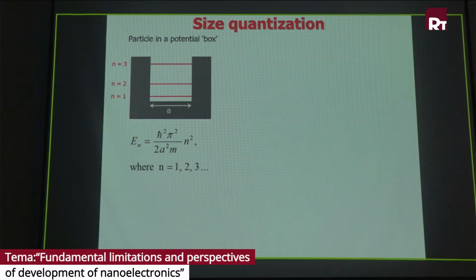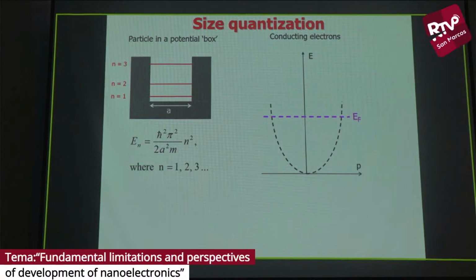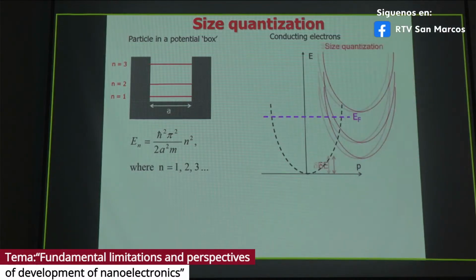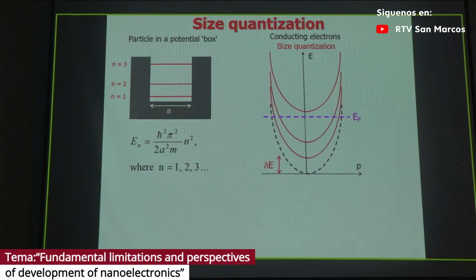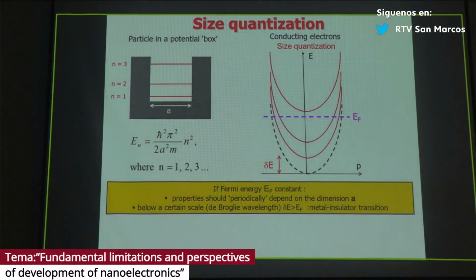Let's recover conventional textbook quantum mechanics. If one takes a quantum particle and puts it in a quantum well of dimension a, and the mass of the particle is m, then the energy is quantized. If we now apply the same quantization rule to electrons in a metal, taking for simplicity the easiest parabolic dependence, then as soon as we start to restrict one dimension, the spectrum splits into different parabolas. And if we stabilize the Fermi energy, this is another story how to do it, I'm not going to expand on it, it appears that each time a size-quantized level crosses the Fermi energy, we should have a singularity in the density of states, which corresponds to an increase of the electric conductivity. And another very important story: when the lowest level goes above the Fermi energy, it means that we will have a transition from metal state to insulating state.